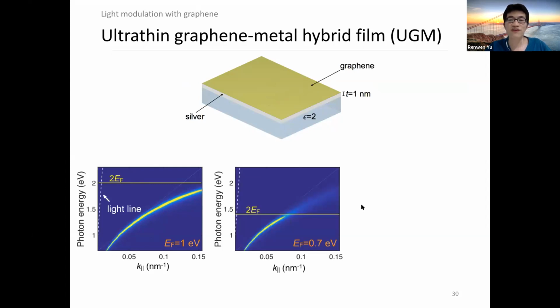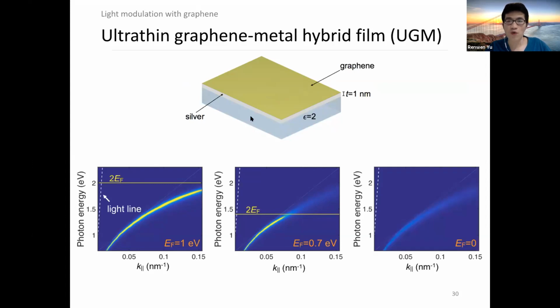However, when we decrease the doping level of graphene, we can see that the plasmon resonance with energy larger than twice the doping level is damped. And furthermore, when graphene is undoped, the dispersion is completely blurred in this broad photon energy range. So this means with this hybrid structure, we can do light modulation.